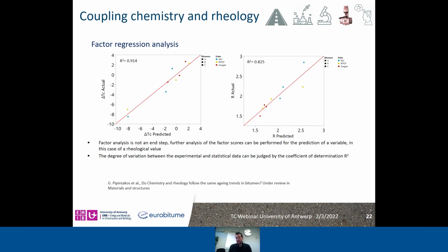But for more basic rheological parameters like viscosity, it was shown, which is not presented here, that if one overloads the model, then the prediction is probably not the best. So for less advanced parameters in terms of rheology, compared to those based on different calculations like the delta TC, one should not overwhelm the model. The degree of fit between the actual and the predicted values can be expressed by the coefficient of determination, and the closer it is to 1, the better the correlation one can achieve.